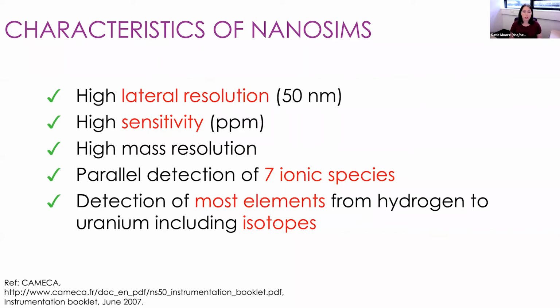The high mass resolution capability allows us to distinguish between species that have nominally the same mass. So for example, at mass 32, sulfur has a mass of 32, but also two oxygen atoms bonded together also have a mass of 32. But the high mass resolution of the NanoSIMS allows us to separate out those two species very clearly, so we have confidence that we know exactly what we're looking for in the NanoSIMS.